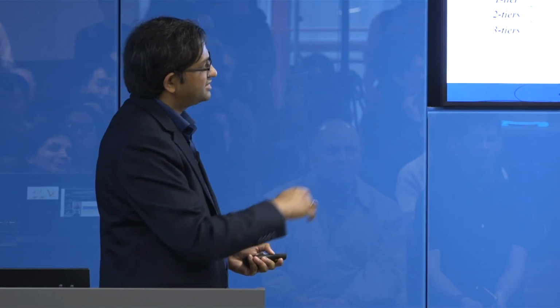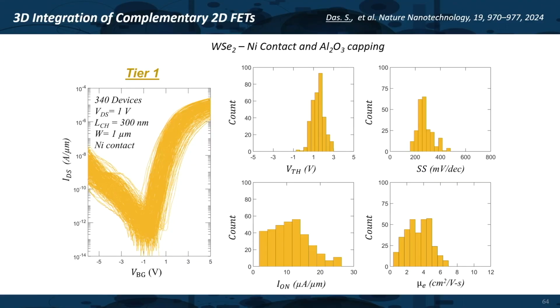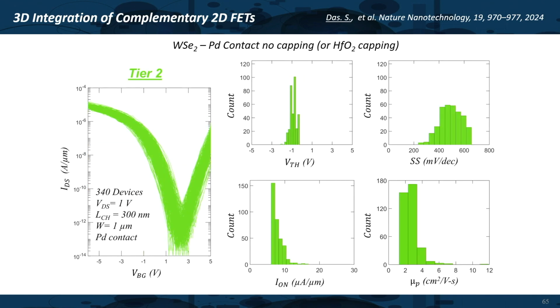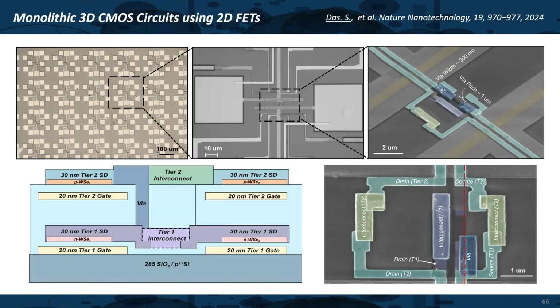So now the next step is that, okay, we have got unipolar transistors stacked on top of each other. Can we do CMOS capability? So we found that tungsten selenide is a very interesting material, because if you put nickel contact and do alumina capping, you get a very nice n-type characteristic from tungsten selenide. But if you change it to palladium as the contact and hafnia as a capping layer, then you get a very nice p-type characteristic. So now I have both n and p characteristics from the same material. So can't we start building 3D CMOS capability?